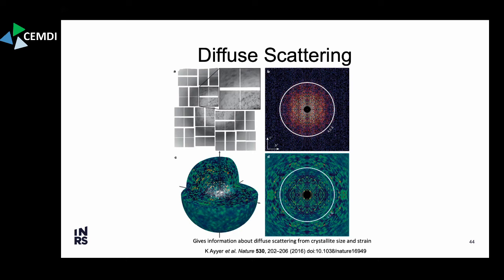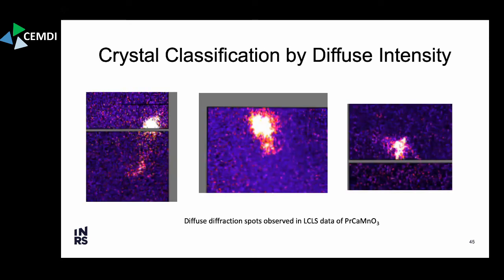So this is the state of the art, we're just starting to get these big data sets of diffuse intensity. And so then being able to interpret this information, what is this telling us? In this case, they were able to use this in order to extend the refined structure of photosystem 2. But like I said, there are many different things that contribute to the diffuse intensity that you see. And so there's still a lot of room to work in order to analyze this diffuse scattering intensity in reciprocal space. And what I would like to do is then do crystal classification, basically looking at this diffuse intensity around a Bragg spot.